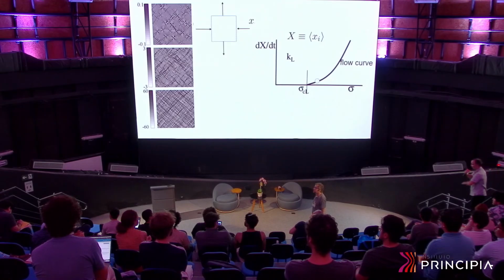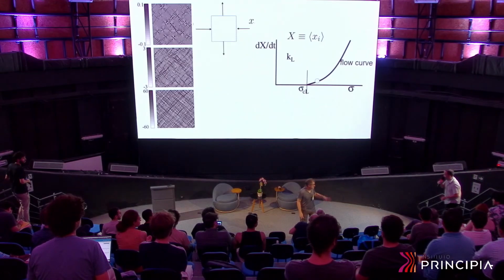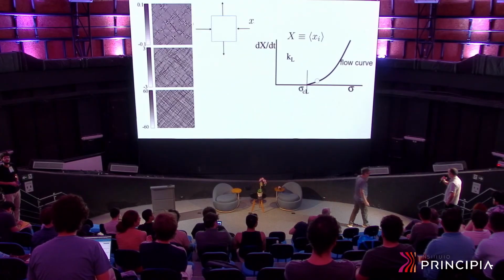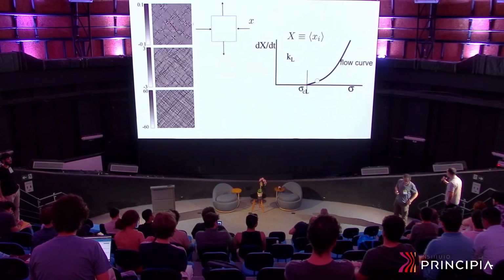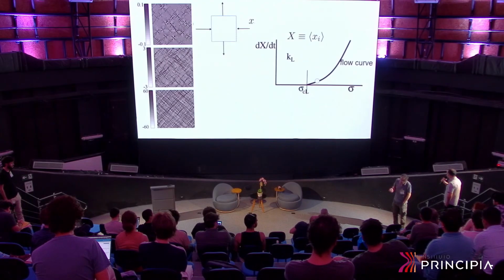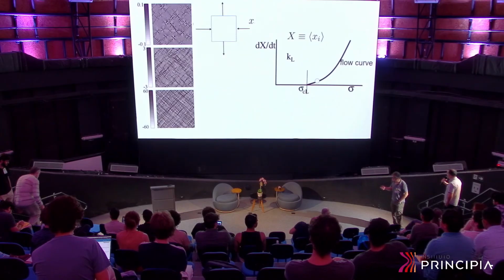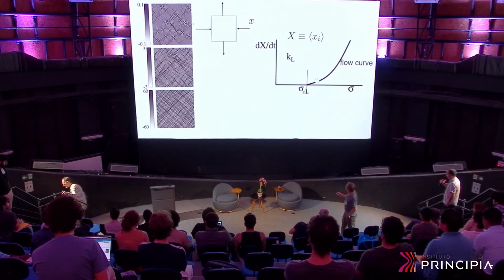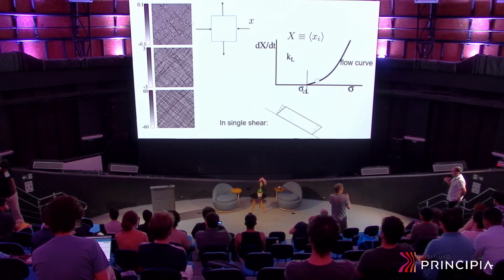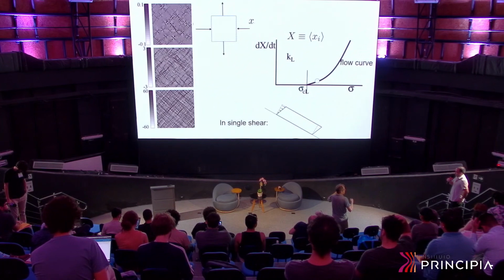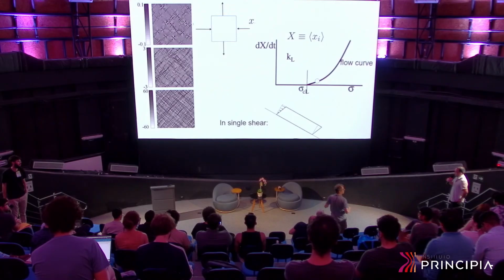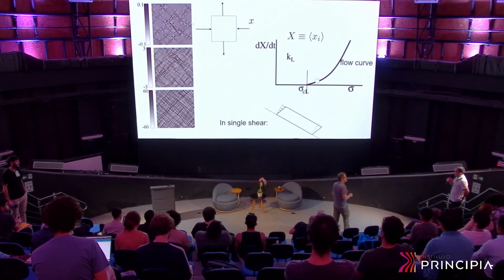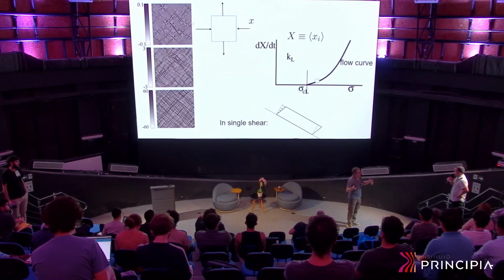I have a quick question myself here, Eduardo. In the pinning case, what's the pinning scenario? Is that collective weak pinning? You can do it for different forms of the pinning potential, but typically we think of uncorrelated short-range pinning centers, which sum up to some typical disorder potential that has some properties. They can be long-range correlated, but usually we consider the case of short-range correlation of the potential.